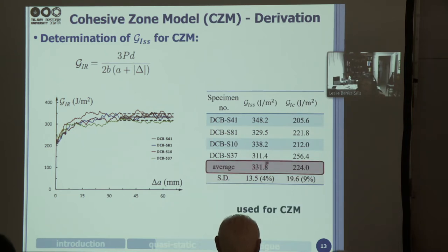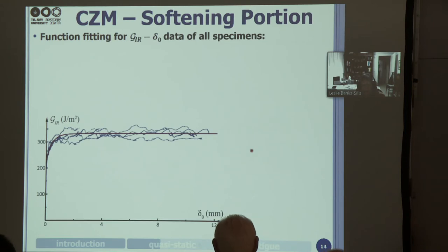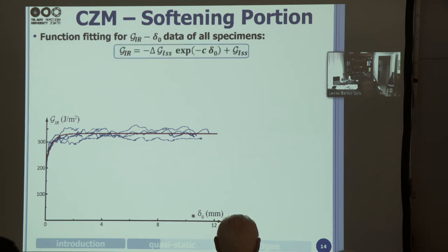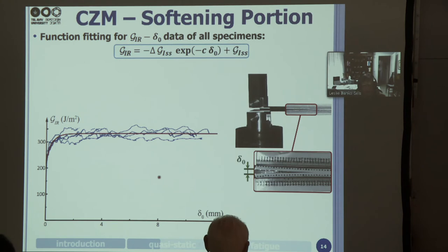And we use these two values in the cohesive zone model because G1C is the area under the first part of the curve, and delta G1SS is the area under the second part of the curve. And we need other parameters in order to prescribe our cohesive zone model. So if we draw G1R now with respect to delta naught, and I remind you that delta naught is the opening at the initial position of the artificial delamination, and we do that so we don't have to watch something that's moving. We just measure this as it changes.